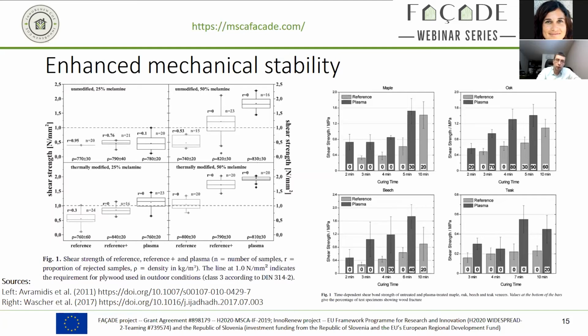In this case, it's already just different wood species. The same is true for different bio-based materials, and also for other materials. Even if I have the same base polymer, the residual additives or the residual monomer content within the specimen can make a difference for the absolute effect of the plasma treatment. So between different batches, there might be some variation, even for polymers that are quite well controlled.